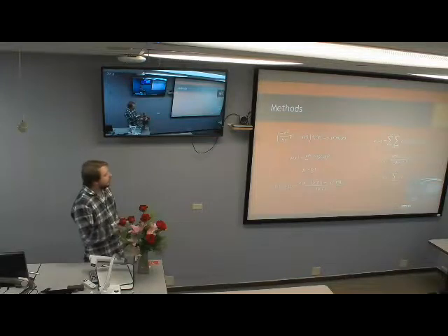So you're saying it's because... You probably were on the right track. I think I didn't really catch what exactly you're trying to say. So I was kind of pointing towards the oscillator strength. So what happens with oscillator strength? It depends on the dipole moment and the dipole moment matrix elements, and if those are forbidden. And so these low transitions, HOMO-LUMO transitions, are not optically active.